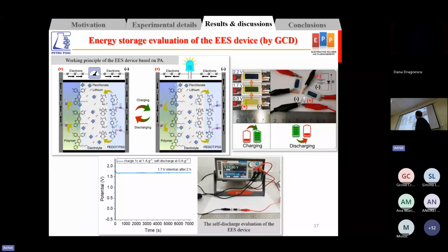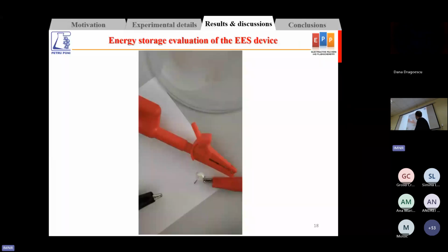Since the device retained up to 1.7 volts after 2 hours, we plan to test this as an energy source. So we connected the two devices in series, and we powered a 3 volt LED for about 30 seconds. Here I have a short video. It's only 30 seconds, but the device is still lighting up to 10 minutes, though the light is very faint.